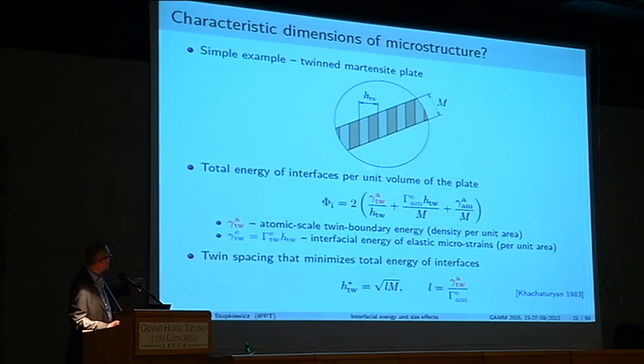If we now evaluate the total energy of interfaces in this system per unit volume, you will see two main contributions. The one in red is inversely proportional to H twin, which means that the finer the microstructure, the more energy we have in the interfaces, of course. So from that, if we want to minimize the energy, we would like to make the microstructure as coarse as possible. However, the other term is opposite. The finer the microstructure, the smaller H, the lower the energy.